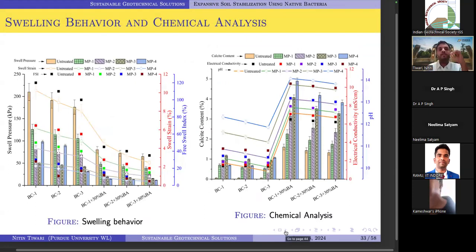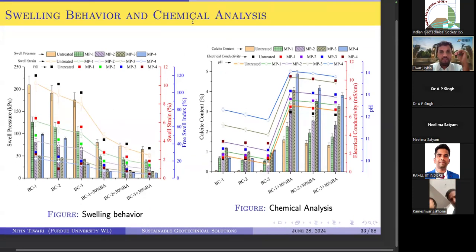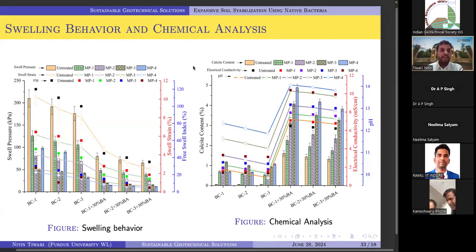Then we move to the other area and check what exactly is happening. Anyways, we check swelling pressure. As I mentioned initially, when it comes to expansive soil, swelling and shrinkage are the two problems. So our target was to check the swelling pressure. Just to clarify, if you're not able to observe it, initially you can see the swelling pressure, then there is a swelling strain, which is with the line diagram. And these black dots and the other dots you're seeing are the free swell index.